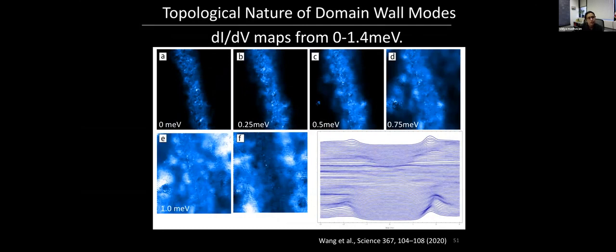And then you can do other checks. This is just one example of a check. You can take density of states maps as a function of energy. Right at zero bias, this is the domain wall. You can see that at zero bias, you have a nicely confined state living exactly in the region of the domain wall. As you increase energy, the width of the state, the spatial extent, actually increases.